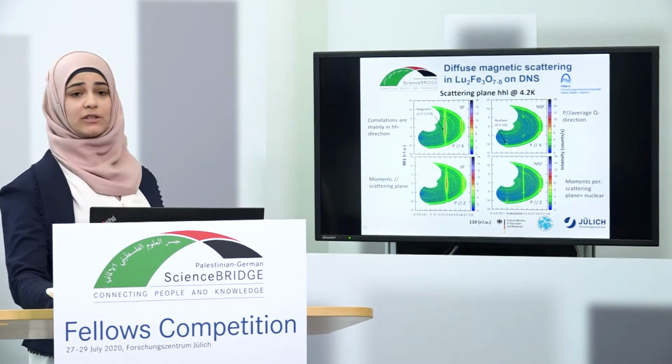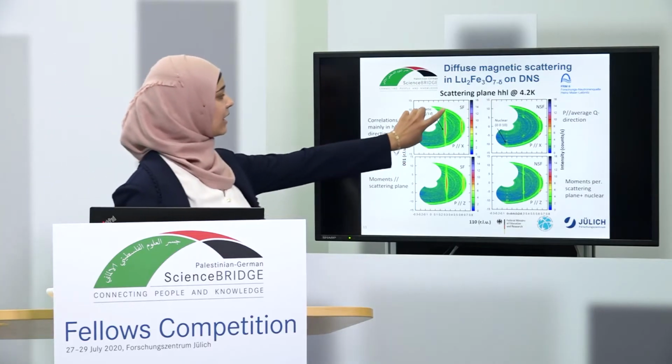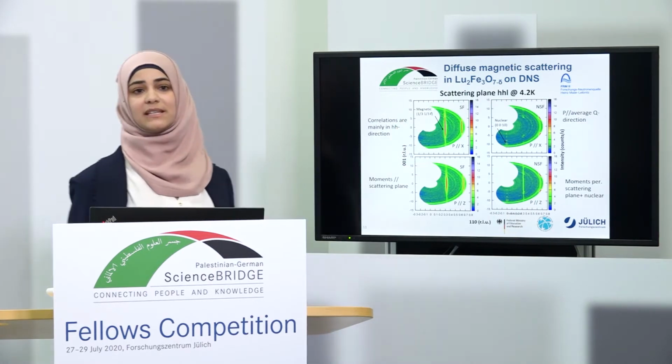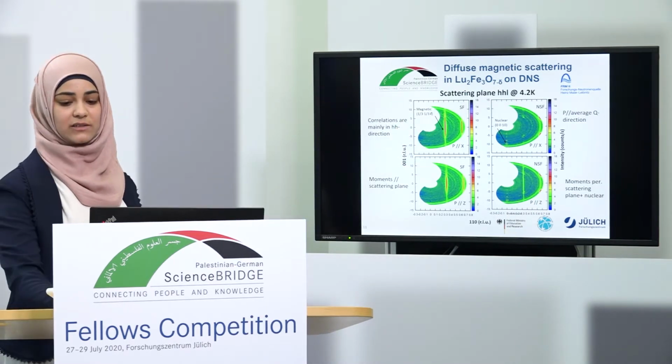Okay, I also took these crystals, but now large-size crystals, to the reactor FRM2 to measure polarized neutron scattering at DNS. I wanted to check, in fact, if the large crystals exhibit diffuse scattering or magnetic superstructure reflections. And as you see, I got diffuse scattering, which means the samples do not really show a